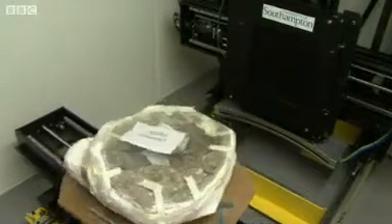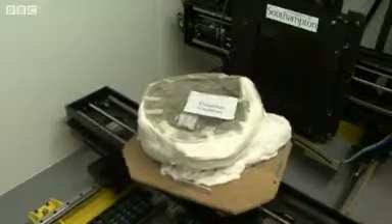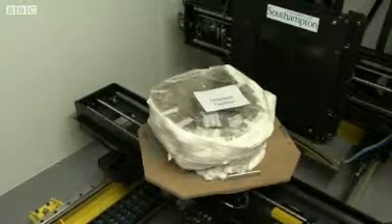The detector is about 40 centimetres wide. The cauldron is more like a metre wide, something like that. So in order to scan the whole of it, we had to shift the panel to one side, take a few radiographs, move it across, move it across, move it across. We actually used 4 positions. The cauldron was scanning for a whole weekend, but when you compare that to 600 hours of man time excavating it, it's relatively short.